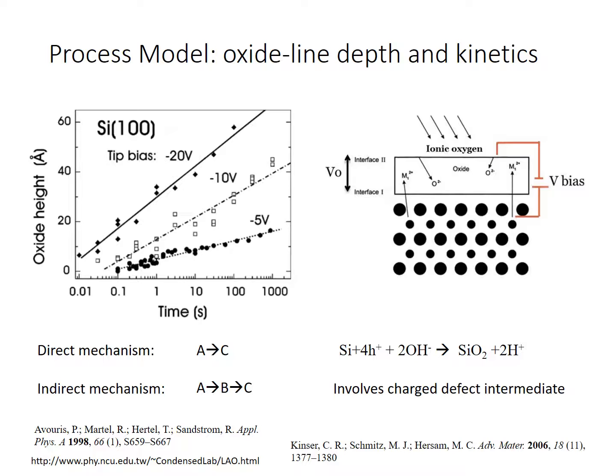Finally, I'll talk briefly about the kinetics of the oxidation process. Oxidation in scanning probe lithography has been shown to occur via both a direct and an indirect mechanism. The direct mechanism is shown in the equation here on the slide, and the indirect mechanism involves a charge defect intermediate. The initial oxide layer grows rapidly in height through the direct mechanism, but over time, space charge builds up by the indirect mechanism, which prevents further oxide growth.